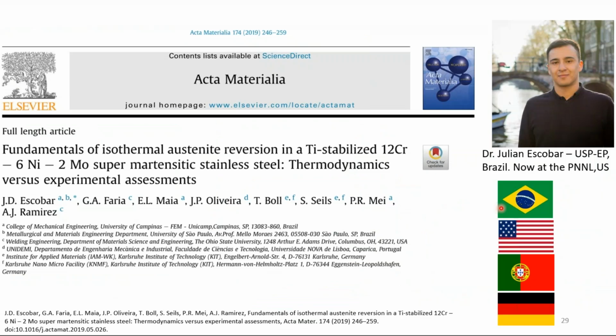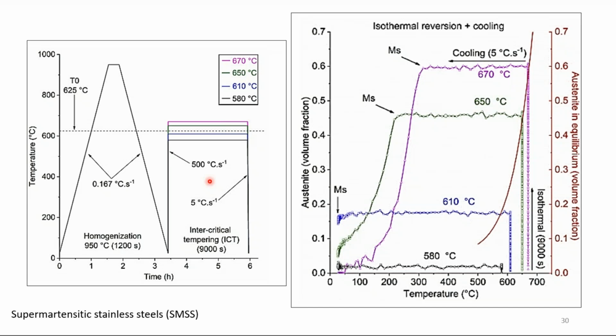That's very interesting. This is another study conducted by Dr. Julian Escobar. This study has a collaboration from different researchers from Brazil, the United States, Portugal, and Germany. In this work, he studied a super martensitic stainless steel, and he conducted a similar test. He did the homogenization in the Gleeble, and then he applied some isothermal treatments. During these isothermal treatments, he used 2 temperatures above the T0 temperature and 2 temperatures below this T0 temperature.